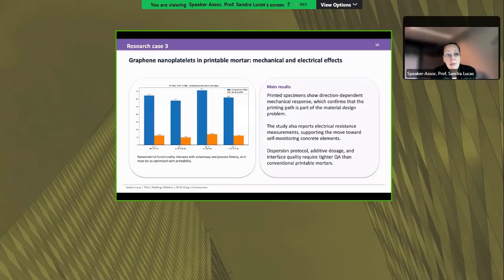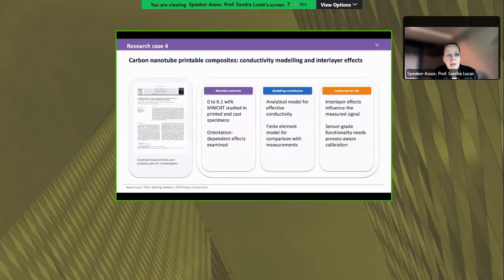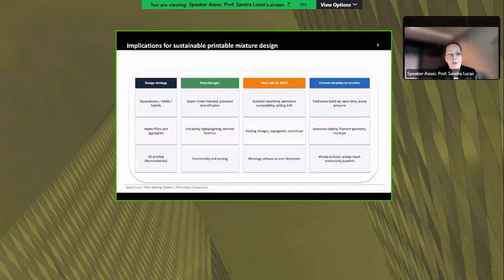So we printed specimens again, but this time on a much smaller scale. We explored the use of graphene nanoplatelets, but then we moved to the carbon nanotubes. For the work, we managed to develop and to study the conductivity and to do it on a small scale. But we also faced, again, some problems, especially when moving to the large scale. So in this design, with the different design strategies that we selected, there are some variables that we still need to monitor and we can't fully monitor.